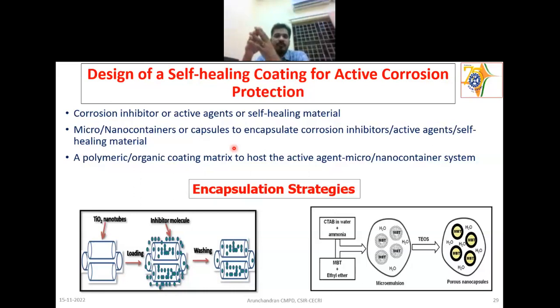Then later they found that some of the polymeric capsules do not have enough mechanical strength. When you add these capsules inside the paint, in the laboratory we may make some 100 ml or 50 ml paints in one beaker and coat. But when you make it at the industrial level, you will have bigger reactor vessels and the mixing will be quite rapid, and in that case it was found that many of these capsules are rupturing very quickly. And even when you keep them in the polymer layer without mixing, some of the polymeric bonds are rupturing and the healing agents are being released prematurely.